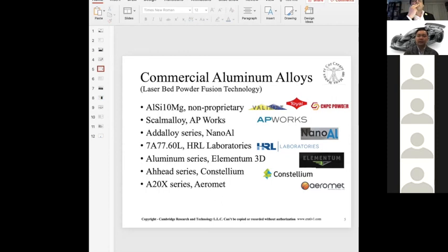Yeah, great question. Couple ways. One is to take a keen eye on the powder feedstock, so the amount of oxygen. I mentioned earlier that these defects are usually caused by what the industry calls spatter. But if you do a chemical analysis on this material, there are some oxides, carbides and organic compounds. So if you give the supplier an upper limit of how much oxygen or carbon you can allow in your material, you can expect the end product to print with less of this spatter.